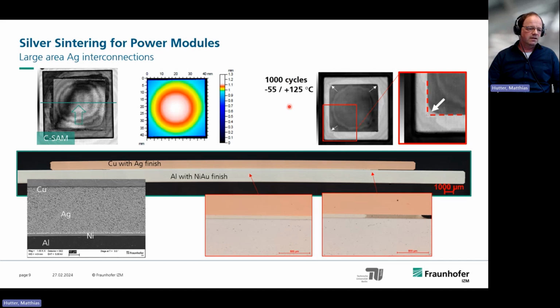You see, we have carried out some reliability tests, and you see that even after 1,000 cycles passively tested, we have only a very small amount of the area deteriorated. The crack propagated from the corner a very short distance inside. So this would be totally different if you compare it to an ordinary solder joint, which we have done, which is not shown here.